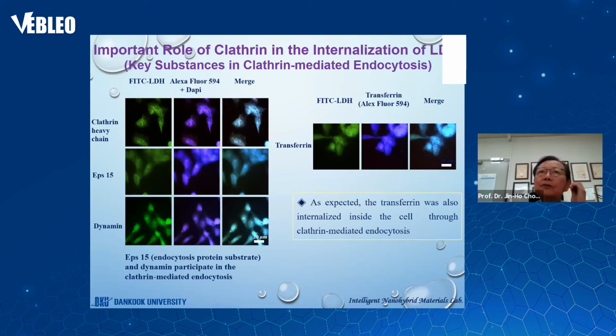We incubated the whole cell with the FITC-LDH, as I mentioned before, and stained them with the antibody against clathrin, dynamin, and EPS15, with Alexa Fluor 594 conjugated to the secondary antibodies as the probe. And we found that the FITC-LDH was well co-localized with clathrin, dynamin, and EPS15. EPS15 plays a critical role only in clathrin-mediated endocytosis by associating with the plasma membrane receptor, the AP2 protein, which is essential for receptor-mediated endocytosis.